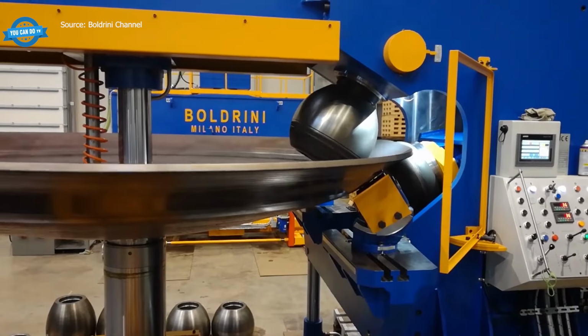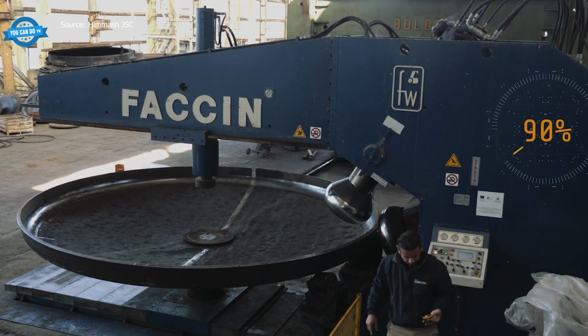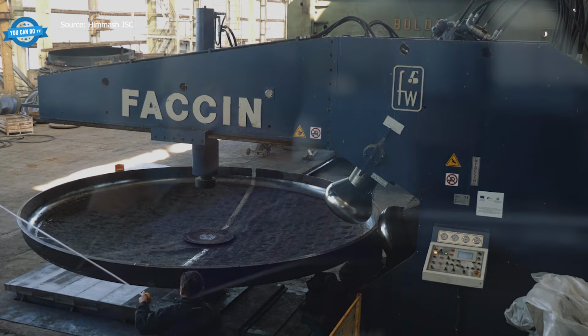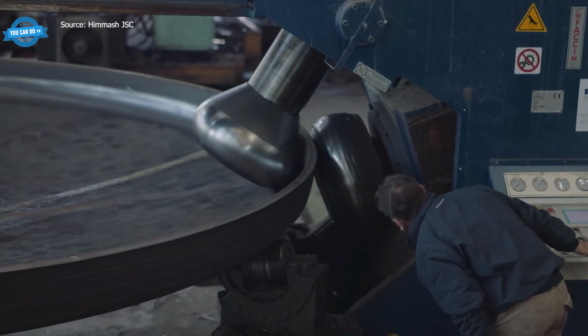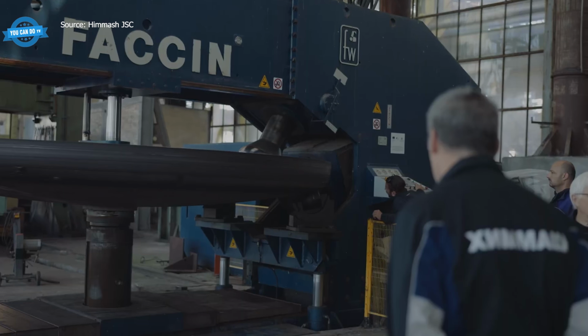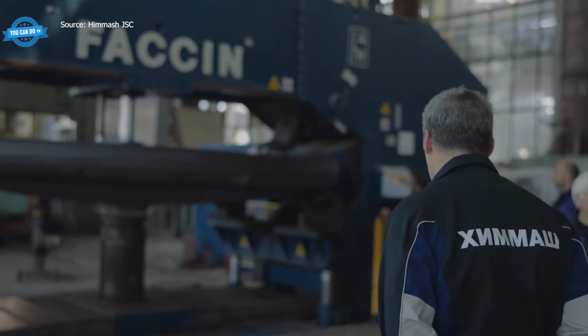This highlights the scale and precision required when forming thick steel edges for large offshore structures. A flanging machine shapes the edge of a 4.5-meter circular plate, rotating it through pressure rollers until the inside diameter is reduced to 4.3 meters. The finished circumference reaches 13,502 millimeters, with minimum plate thickness measured at 36.6 millimeters after forming. Uneven forming can damage coating adhesion or create small pockets where seawater and oxygen remain trapped. Splash zone areas are especially demanding because repeated wet and dry exposure accelerates corrosion faster than continuously submerged sections.